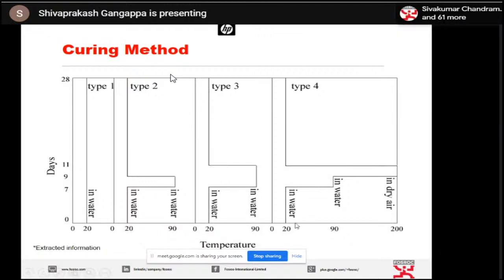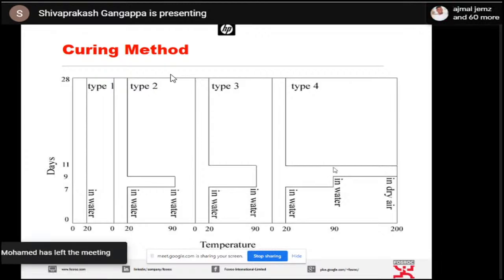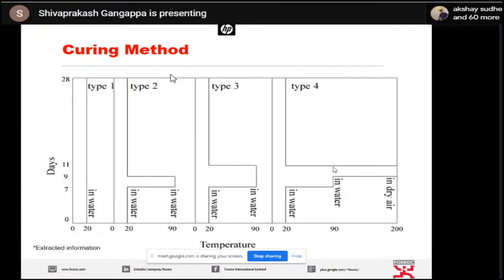The most important thing to be noticed here is the last part. The first 7 days are at 20 degrees. After 7 days, the water temperature is increased to 90 degrees up to 9 days. After 9 days, we take the cubes out of the water and put them in the oven, where the oven temperature is maintained at 200 degrees. After 200 degrees, it will be in for 2 days. Again, we bring the concrete cubes back to water for 28 days and we continue. Probably to understand this takes a little bit of time. Probably in the next slide, you'll be in a better position to understand.